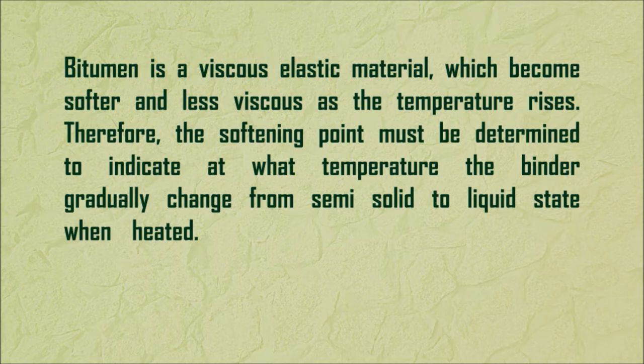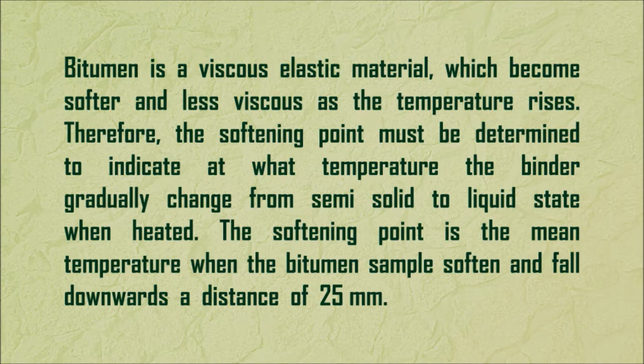Therefore, the softening point must be determined to indicate at what temperature the binder gradually changes from semi-solid to liquid state when heated. The softening point is the mean temperature when the bitumen sample softens and falls downwards a distance of 25mm.